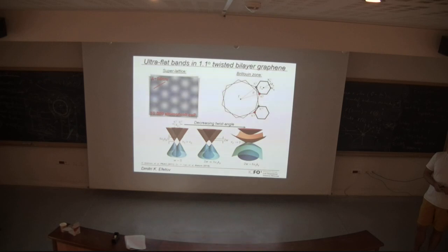Okay, and basically the whole trick was that if you transfer two layers of graphene one on top of another, and you make a very sharply defined twist angle of only 1.1 degrees between those layers, the so-called magic angle, really interesting things happen, where K points between the top and bottom layer are very close in K space to each other, and they start hybridizing. And then people like Allan MacDonald discovered that for very specific angles, flat bands arise where the Fermi velocity drops to zero. Because kinetic energy is now quenched in the system, the Hamiltonian is mostly defined by the interactions, and all sorts of interesting interaction physics was expected, but is now also observed.